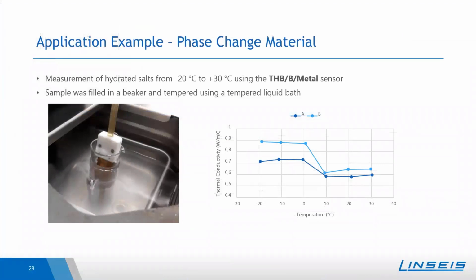Within the next slides, I have prepared some application examples. So here on this slide, you can see the measurement of 2 hydrated salts. The measurement was performed from -20 to +30 degrees Celsius, and a THB metal sensor was used, so a small metal-framed THB sensor. The sample was filled in a beaker, and the beaker was put into a tempered liquid bath to be able to set the different temperatures. The sensor, as can be seen here, was just hung into the material, and then the measurement was performed.